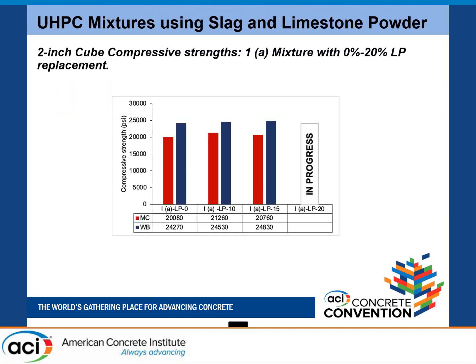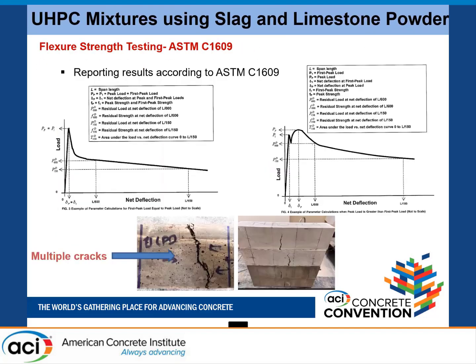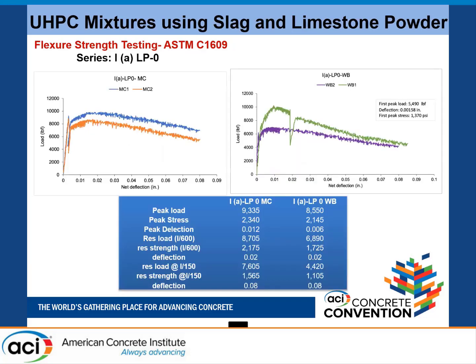And then we investigated some flexural testing here. We used ASTM C1609 testing, and these are only for fiber UHPC materials, because of how the fibers are actually increasing the tensile capacity of the beams. So this is no limestone powder content. There is no limestone, only slag.